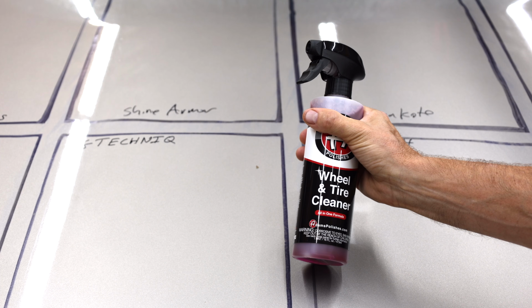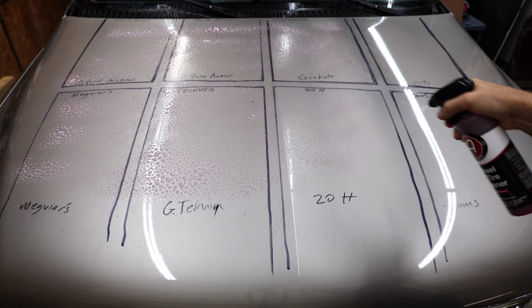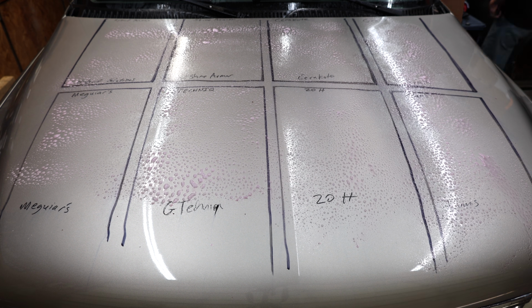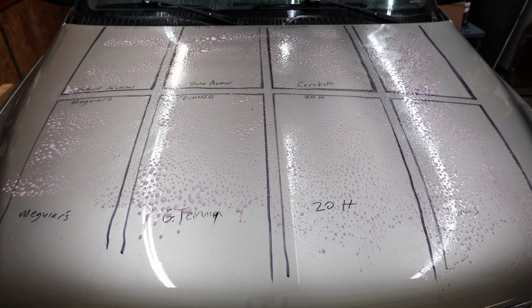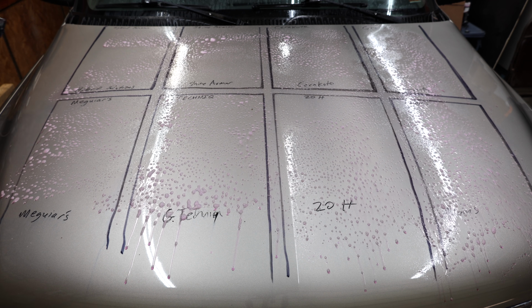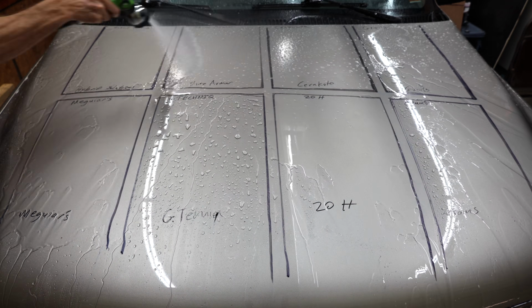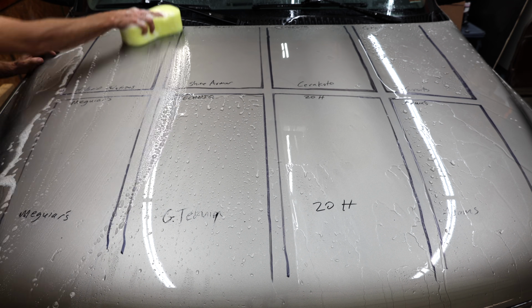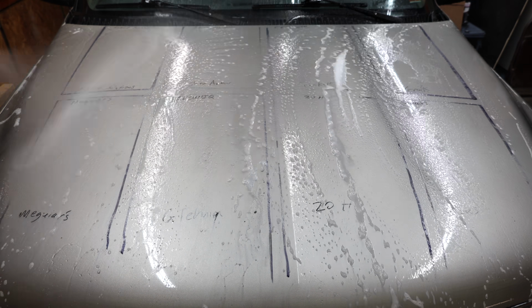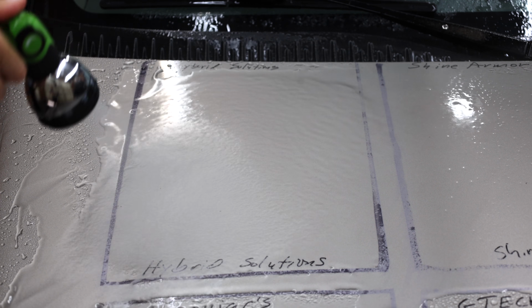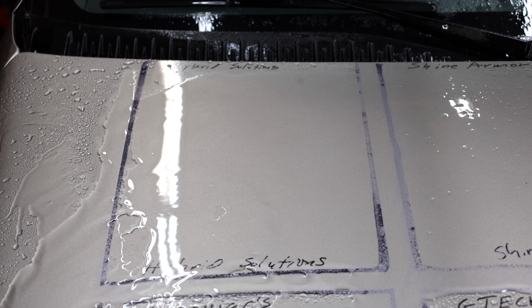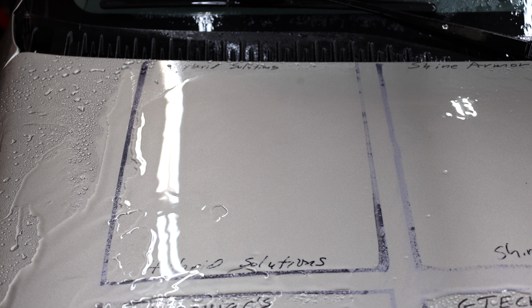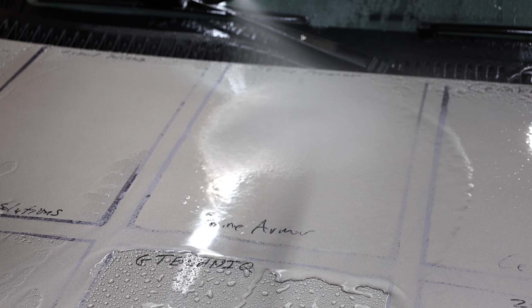Wheel and tire cleaners oftentimes contain powerful ingredients such as acid, sodium hydroxide, as well as powerful solvents. The wheel and tire cleaners had a full minute to break down the coating, so I'll go ahead and rinse off the wheel and tire cleaner and we'll use strip wash to make sure that all the wheel and tire cleaner has been removed. And even the permanent marker is beginning to come off. The hybrid solutions has performed very well throughout the showdown, but the wheel and tire cleaner pretty much destroyed the hybrid solutions.